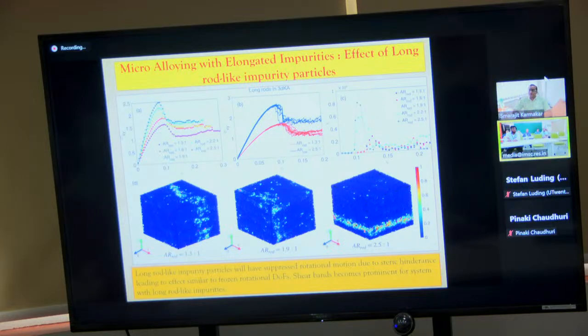When you shear the sample, do you allow them to move or not move? In this scenario, they are free to do both rotation and translation. But just because they are elongated, their rotations are hindered very significantly. Their aspect ratio here is around 2.5. It's not very long, but I think 2.5 particle diameters. Thanks.